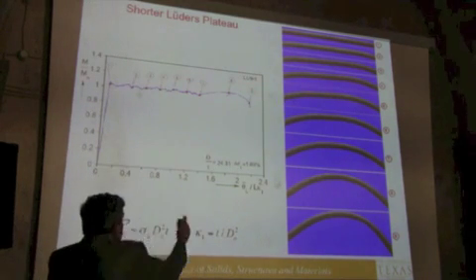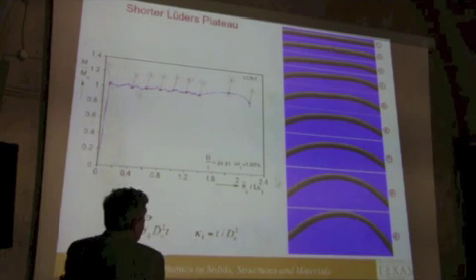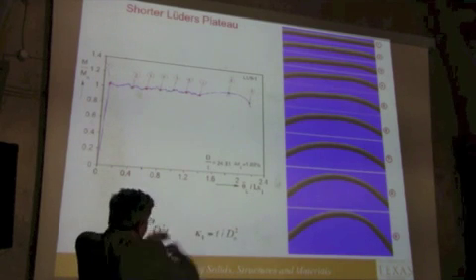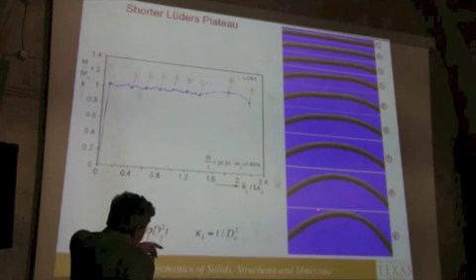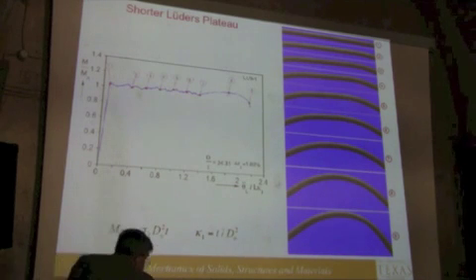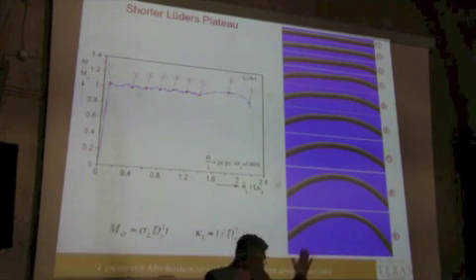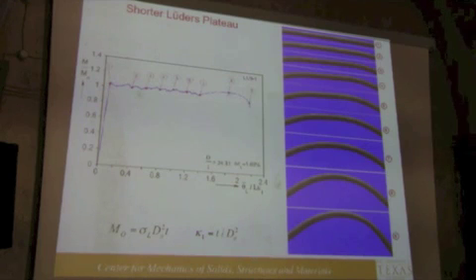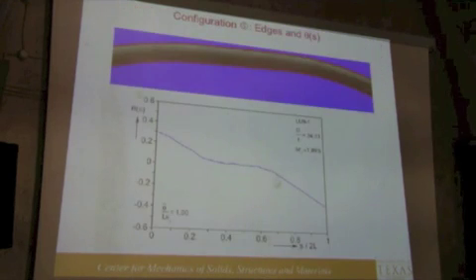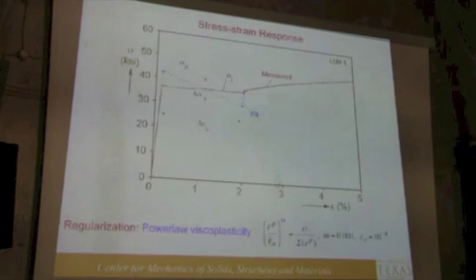And as we go on, the two high curvature regimes move in, and then at the end we have this. Uniform again. Start uniform, end up with uniform, plateau in the middle, but in a moment. You see here the two different curvatures. I am going to just tell you what happens if you put that kind of stress-strain curve in the material of the structure.